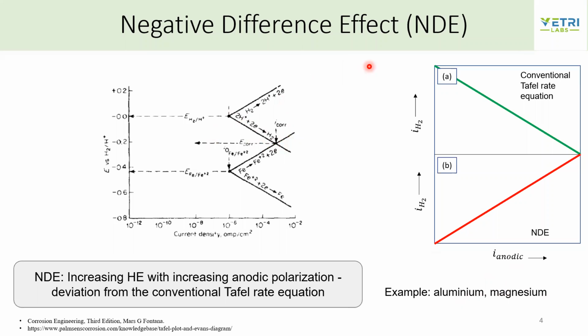But in metals such as aluminium and magnesium, hydrogen evolution actually increases as the anodic polarization also increases. So if we were to plot hydrogen evolution current density versus anodic current density, a conventional Tafel rate equation would mean that it decreases. But during NDE, the negative difference effect, this hydrogen evolution current density increases along with the anodic current density.